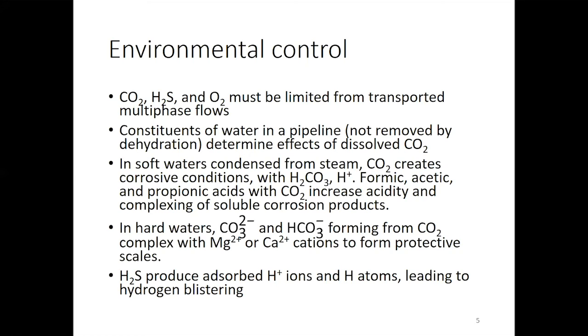H2S produced, of course, as we knew, adsorbed hydrogen protons and adsorbed hydrogen atoms that would lead, of course, to hydrogen blistering. These are the basic constituents that drive corrosion at a high rate in the beginning, but with time, they contribute to decelerate naturally corrosion in a typical oil pipeline.